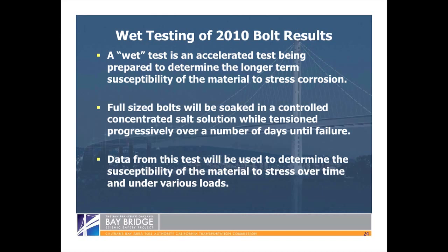We're trying to simulate a long-term phenomenon, which is stress corrosion. And I think we mentioned to you earlier that hydrogen embrittlement and stress corrosion, both of them, are time-dependent. In other words, when you do a test on a material, you don't see it in the material. You have to subject them to conditions that simulate a time-dependent failure.